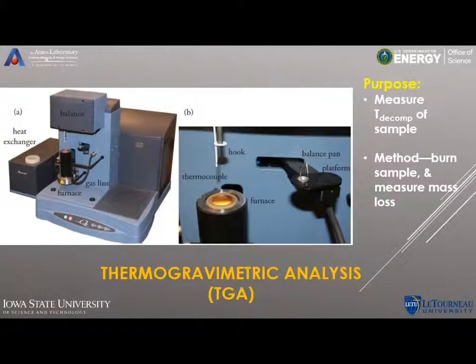The first of these was thermogravimetric analysis, abbreviated TGA. And that works by taking a sample that's placed in a metal pan, and that sample is grabbed by a thin metal hook over here that automatically comes over, lifts this pan up, brings it over, and then lowers it down into the furnace. And then the furnace comes up and the sample is enclosed. There's also a thermocouple there that you can see, and that's measuring the temperature change, because this sample is going to be heated to burn off the material over a range of temperature. And the hook also is attached to a mass measuring component, and that's going to measure the change in mass as the sample's heated and burned away. And so you're looking at the change in mass over a change in temperature.